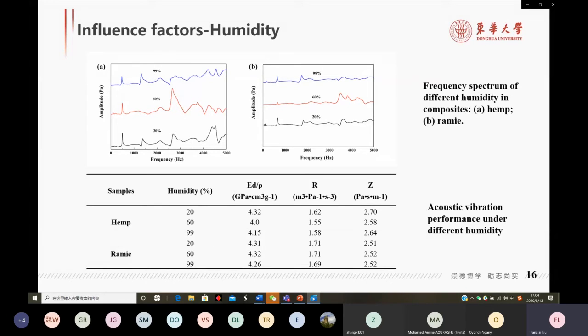At the humidity of 60%, some peaks circles become high, some become low. It may be that the after-water molecules enter the composite materials. It caused a certain change in their density.